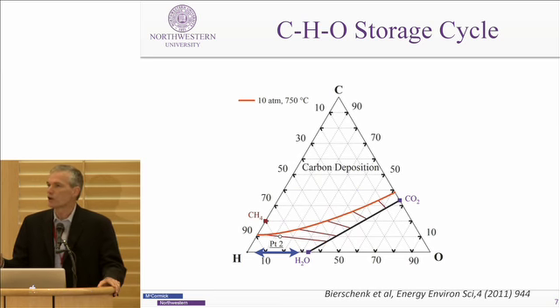So we had an idea for an alternative chemistry where we actually combine both CO2 and steam electrolysis at the same time. So to understand this, I'm going to just introduce quickly this composition map. So to show how we're doing this, here's a map showing carbon, hydrogen, and oxygen and various combinations of compositions of these things. And just to give you a reference point on the bottom, this blue arrow here shows typical steam electrolysis, where you're going from hydrogen-rich to steam-rich and back and forth again.